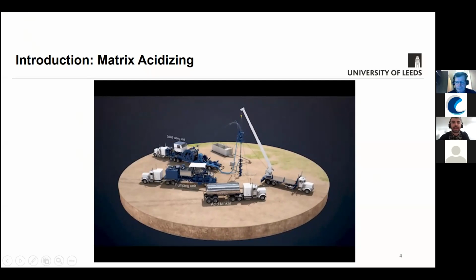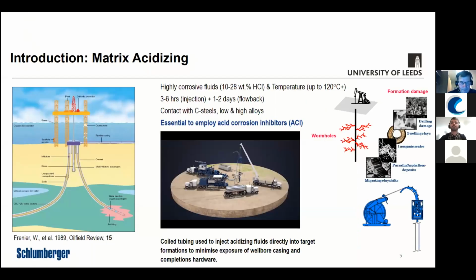Okay, so hopefully everyone heard that okay. So that gives you a little bit of an idea of the purpose of matrix acidizing, essentially to maximize production. But inevitably, the environment comes with certain corrosion challenges. So typically, it's a highly corrosive fluid that would be injected into the well. Normally, high strength hydrochloric acid, and temperatures can be extremely high, depending on the conditions within the well. The injection periods normally last for about 3 to 6 hours, so that'd be the period over which the hydrochloric acid is injected. So during that time, that's a particularly sensitive period where corrosion can be extreme if it's unmitigated.